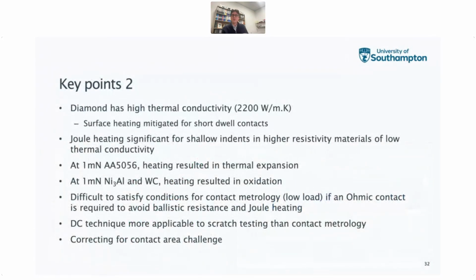So just summarizing those key points from that second section, diamond's actually a really good material for doing these sorts of things. It has an exceptionally high thermal conductivity, so it will get the heat out of the contact for the metallic materials, and you can mitigate it for short dwell times. But if you've got high resistivity materials in there, it is a little bit challenging. So we get thermal expansion with the metallic materials, but for the intermetallics and the ceramic materials, we were getting surface oxidation. So really, we're coming to the point where it's actually really difficult to do this.